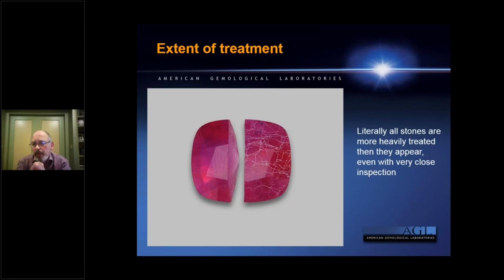This is a statement which I make all the time, that literally all of these stones are much more heavily treated than they appear at first glance, even with close inspection. This was a stone which I had gotten, and relatively speaking, it didn't seem to be that heavily treated with this high lead content glass. So I decided to do an experiment. I cut the stone in half and I etched the surface of the right half of the stone.